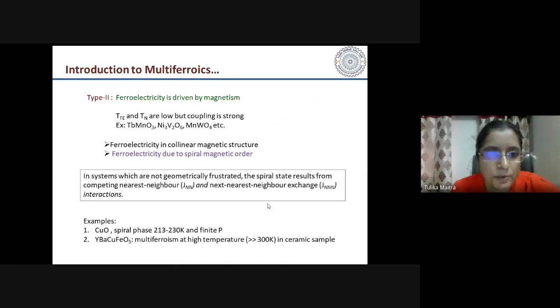And then there is this other class of compounds which have drawn a lot of interest recently because here the ferroelectricity is driven by the magnetism, or the magnetic order drives the ferroelectricity. Here the coupling between the ferroelectricity and the magnetism is very strong, though in the materials found so far, the transition temperatures seem to be low, much lower compared to type 1. So the main goal is to achieve high transition temperatures here, where one can then have very good applications of these materials.